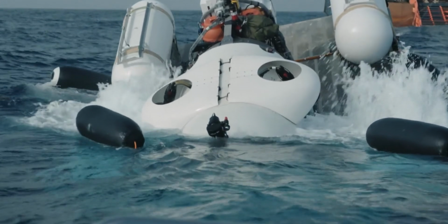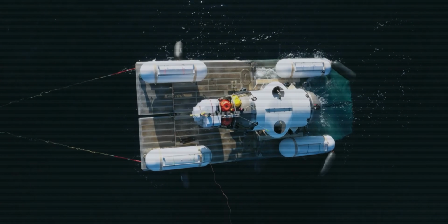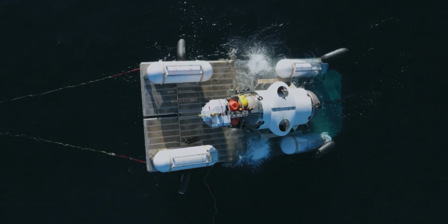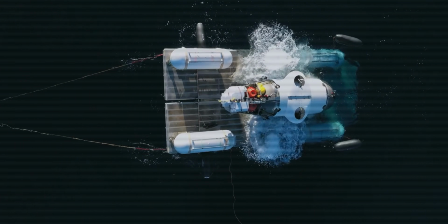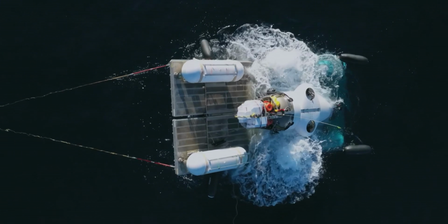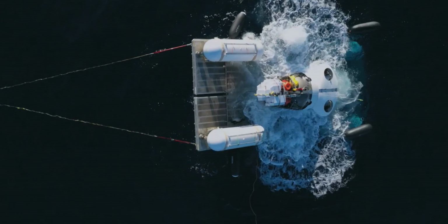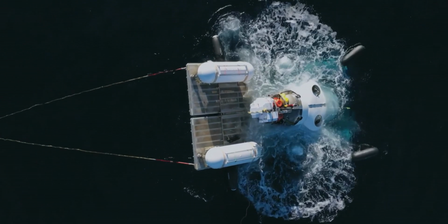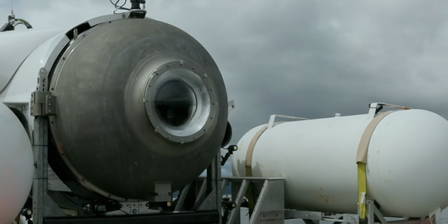Near the surface, where external pressure was relatively low, the separated laminate layers were free to move independently. As Titan descended, the immense hydrostatic pressure forced those layers back together, temporarily restoring much of the hull's apparent stiffness. In effect, the damage became partially concealed at operating depth. When investigators compared the strain measurements with the acoustic monitoring data and the loud bang reported during Dive 80, they concluded that all three pointed to the same structural event. The pressure hull had already sustained significant internal damage nearly a year before the final implosion.